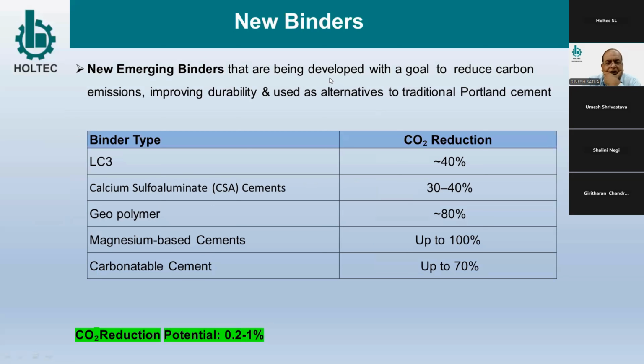The new binders are currently not much in use, still in the development stage, but we can see in another 10, 20, 30 years, these will be very important in reducing CO2. Like LC3, it has a potential of 40%. Calcium sulfoaluminate is another type of cement binder, which uses mainly bauxite, limestone, clay, and some other material, but limestone use is reduced by only 40%. And the burning temperature is around 1200. So it has a potential to reduce CO2 emission.